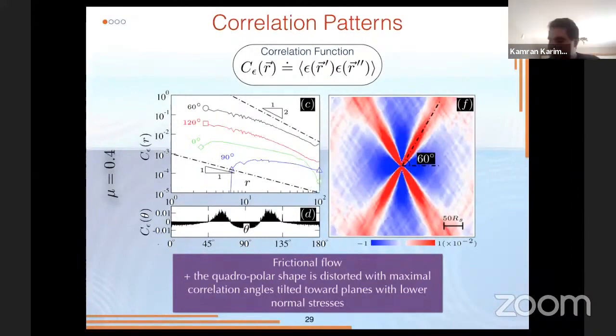Again, a similar data set for the frictional system. This quadrupolar form seems to be distorted due to friction, and we get a bigger angle, almost 60 degrees. If you look at the spatial decay associated with the correlation function, we get a shallower decay, at least along these two angles, 60 and 120, along those shear bands. It's a rather shallow decay up to some characteristic length, and then maybe a faster decay, which might be closer to the 1 over r squared decay for these two angles. And for 0 and 90, we get a steeper decay, or a shallower decay all the way.